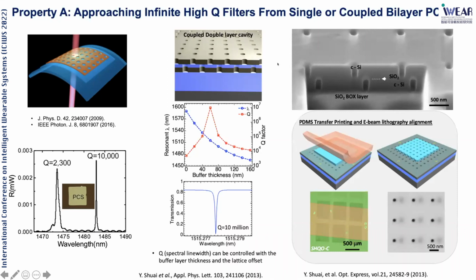You can see that's some schematic and also an SEM image showing this two-layer crystal silicon based on a multi-layer stacking transfer printing process pioneered by Professor John Rogers, where we are able to precisely control the lattice offset of these two layers, so we can, in principle, achieve infinite Q. In some cases, such as sensing or optical design for AR, VR, that Q factor engineering is critically important. In this case, we can leverage this bi-layer structure based on a stacking process to achieve very high Q here.